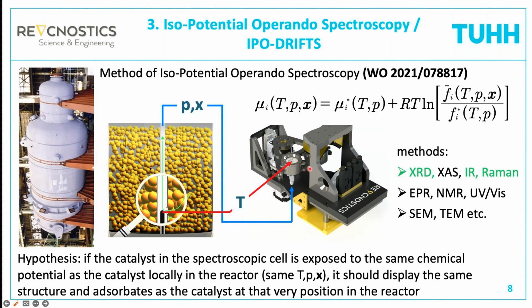And now we put in this spectroscopic cell a tiny amount of the same catalyst that we have in the reactor, maybe a milligram or so, as little as possible, so that we can just measure the spectroscopic information that we would like to measure, but as little as possible to keep the conversion in the spectroscopic cell as low as possible. And when we now separate the reaction mixture from the catalyst, then the chemical reactions stop, because everything is catalytic and happens at the surface of the catalyst.